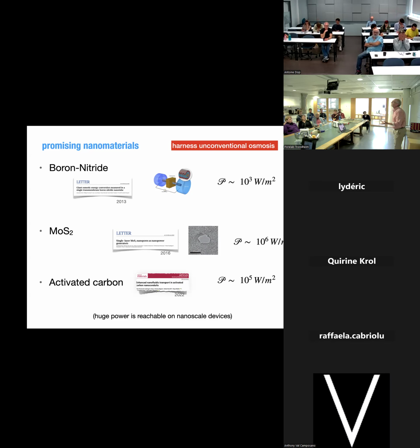One, of course, carbon would be the great material because carbon is easy to fabricate. And actually we looked at what we call activated carbon, or altered carbon. Activated carbon just means that we put it under an electron beam, or you put it in the plasma cleaner, and this raises a lot of chemical groups at the surface, and there, this carbon leads also to very large power.